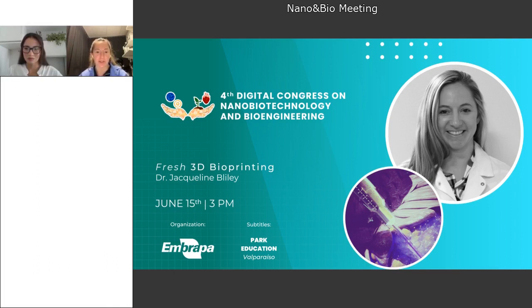One challenge is, as I'm sure you imagine, they're soft, right? So we strengthen certain features of the actual tube that we will be suturing, and we do that either through 3D printing directly by creating a thicker area which is able to be sutured into, or locally cross-linking the area, just so we can have a nice area to actually suture into.